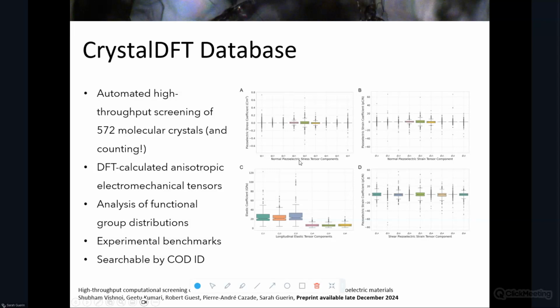So across 600 crystals, we can see where the polarization falls. This positive and negative sign is just because it's charged, so we can have positive and negative polarization in our system. So the average falls around 0, but don't worry, the average is not 0. So we have our pluses and minuses on either side. We have every direction that you can have that response in. We can look at longitudinal piezoelectricity, shear piezoelectricity, and then our stiffness. So even for looking at flexible crystals and mechanically interesting properties, you can also see the distribution now across the wide range of chemistries, again, in both longitudinal and shear stiffness.